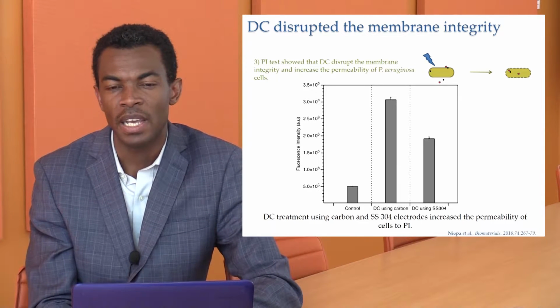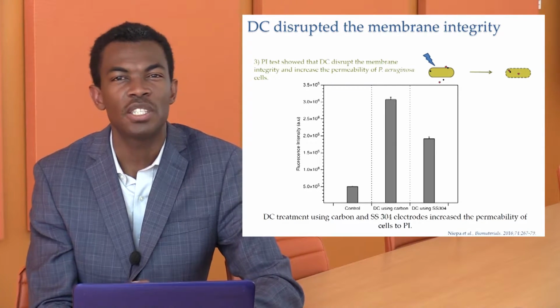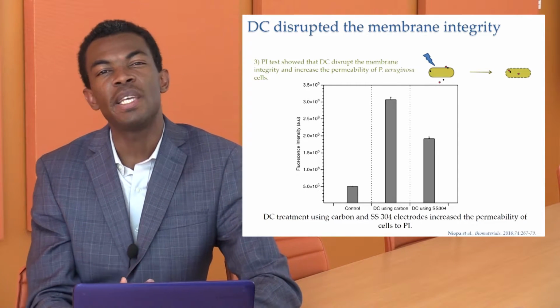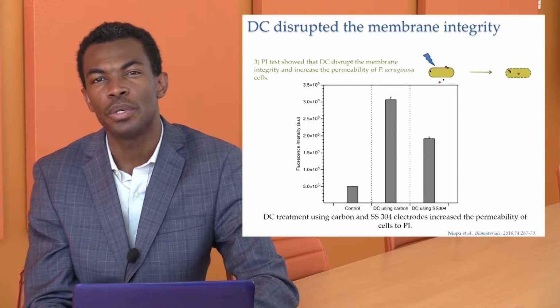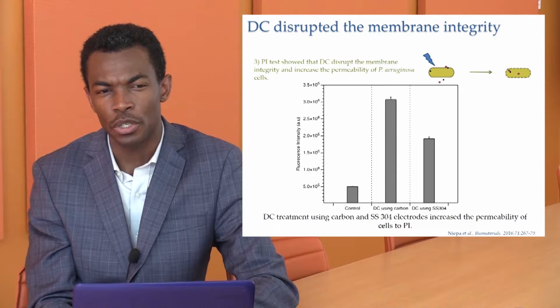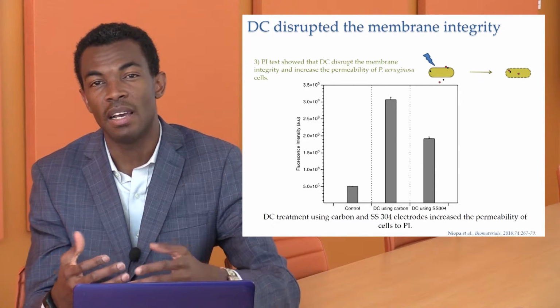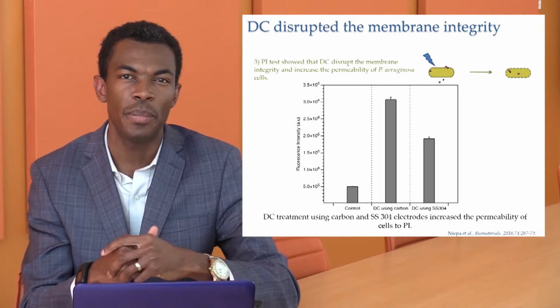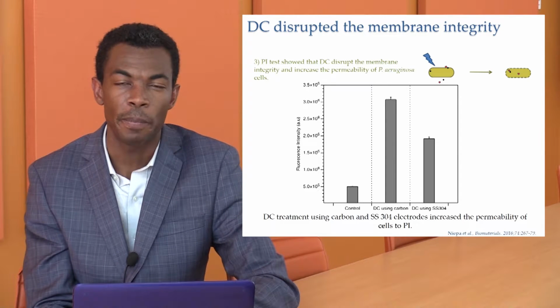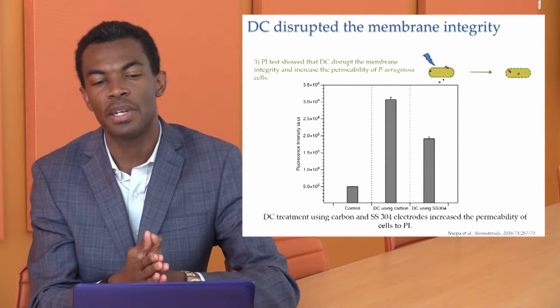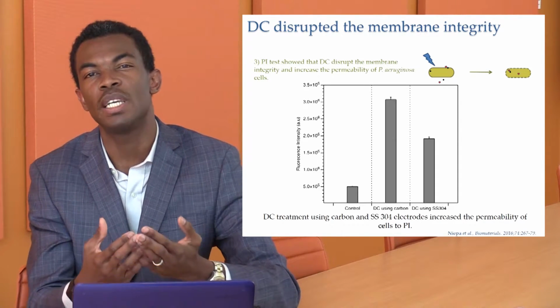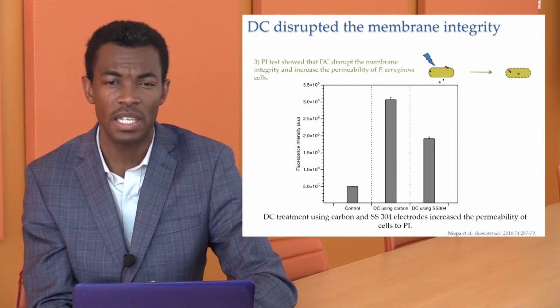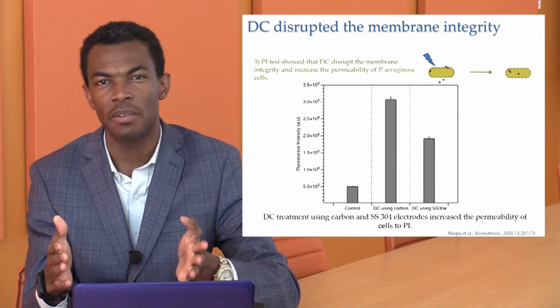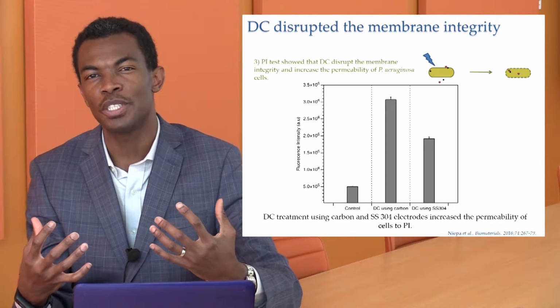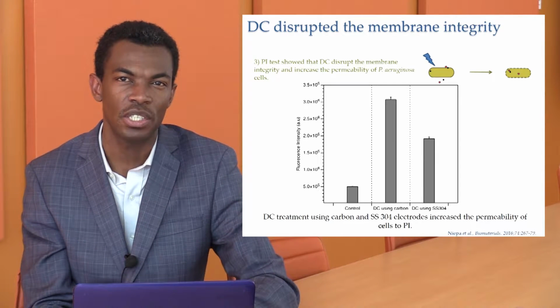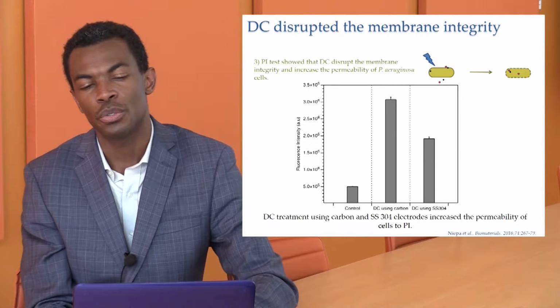To go one step further to confirm our hypothesis, we performed the same treatment using carbon electrode and stainless steel electrode. And then in this case, we allowed the cells to be exposed to propidium iodide. So propidium iodide, or PI, is just a fluorescent probe that interacts with DNA. It is impermeable to cells that are alive, that are intact. When the cells do not have any leakage in the cell membrane, PI will never cross the membrane barrier. But after performing such treatment with carbon electrode, we see that we allow more propidium iodide to go inside the cells compared to when the treatment is performed with stainless steel, which means that the DC treatment somehow permeates the cells. So we see two electrode materials that we're using here, and both of them have different advantages that we can build upon to design a better treatment.